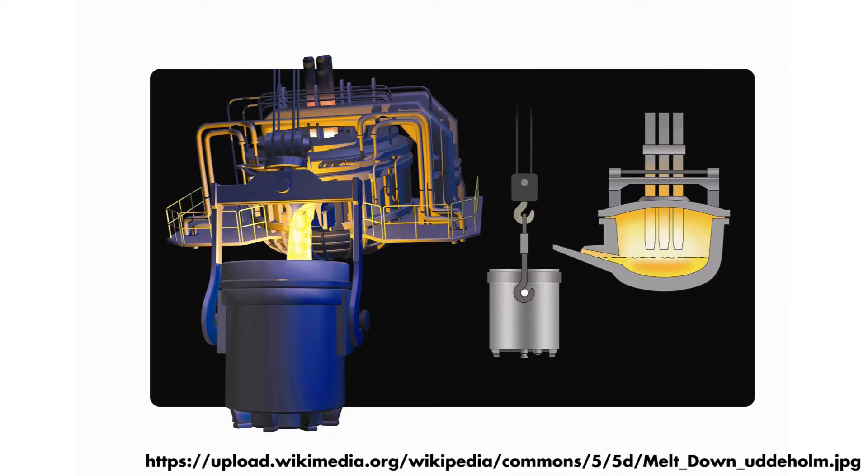A furnace is an oven operated at very high temperatures, usually above 1000°C. After the ore is received from the concentrator as wet concentrates and dried, it is introduced into a furnace and mixed with lime, which acts as a flux to help melt away the gangue, or silicates.